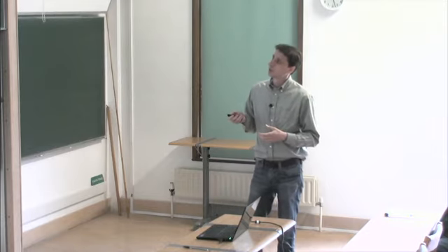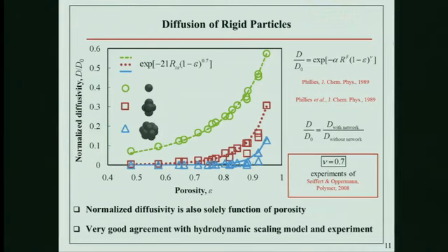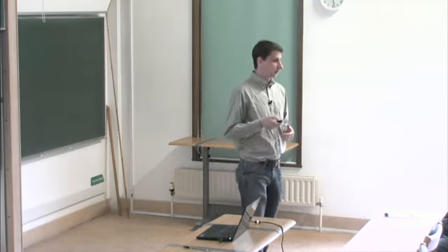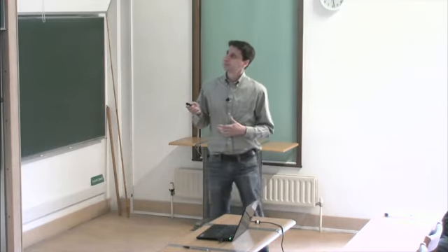We can also compare with hydrodynamic scaling theory, and this is the expression that theory gives us. This is the exponent that we can measure from our simulations, and these are experiments that give exactly the same exponent. All these curves follow the same expression; the only difference is the radius, or hydraulic radius, of the particle, which we can measure independently. We can nicely reproduce the theoretical result and also capture the experimental exponent using our model. So we're happy to see this.